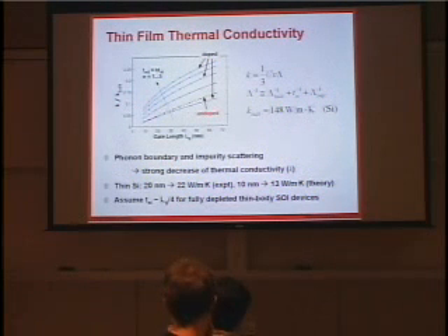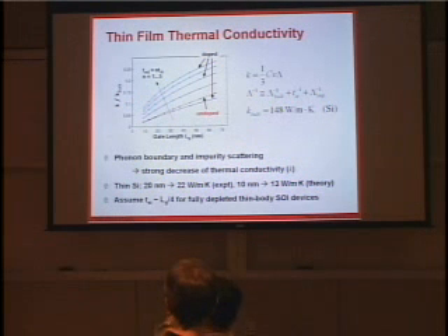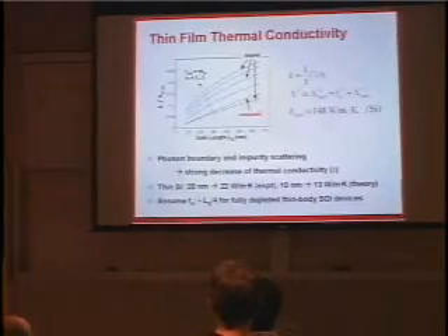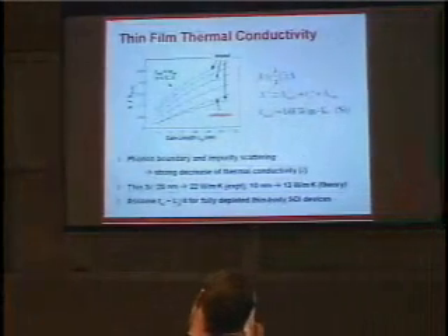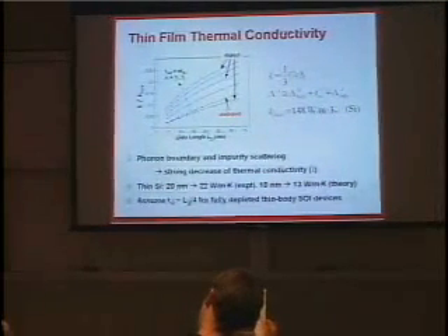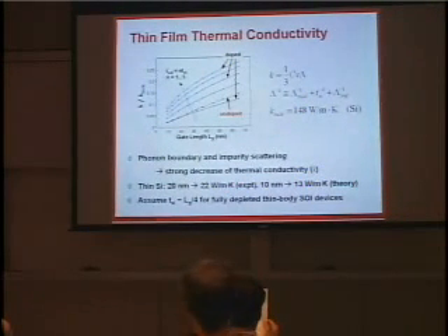So one of the first things that happens when you go to thin films is that the thermal conductivity of the thin film is significantly reduced from bulk. The bulk thermal conductivity in silicon is 148 watts per meter Kelvin. In thin films, it's reduced a lot. Experimentally, the thinnest films that have been measured, by Professor Asheghi's group at Carnegie Mellon, are 20 nanometer thin films, and they've measured about 22 watts per meter Kelvin thermal conductivity.